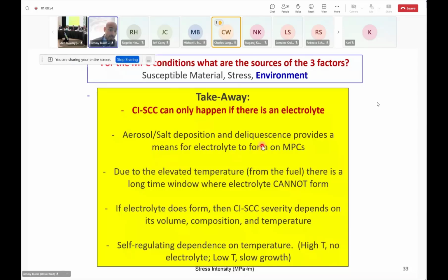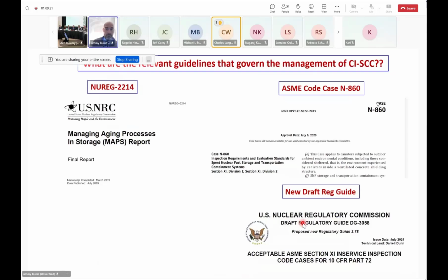If the electrolyte does form, when it does become stable, then the severity of this damage mode depends on the volume, the composition of the electrolyte, and the temperature. And in some ways, there's a kind of self-regulating dependence on temperature. At high temperature, you don't have an electrolyte, but as your temperature continues to fall, when you do get an electrolyte, if it continues to fall, the growth slows down.